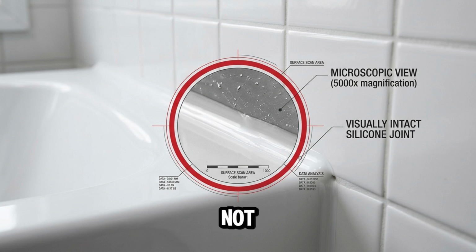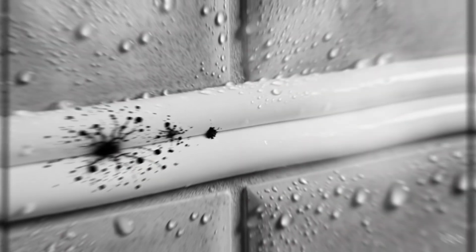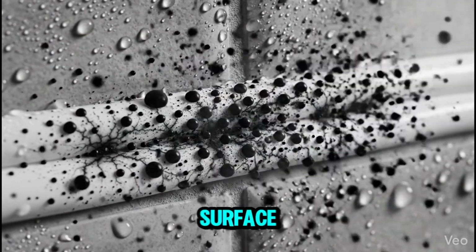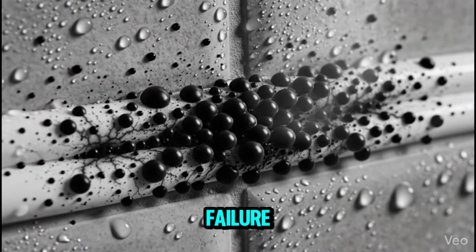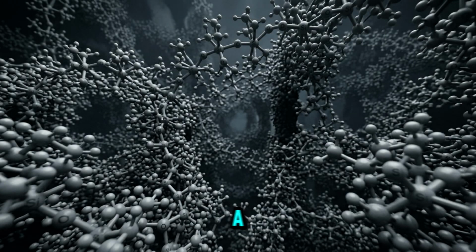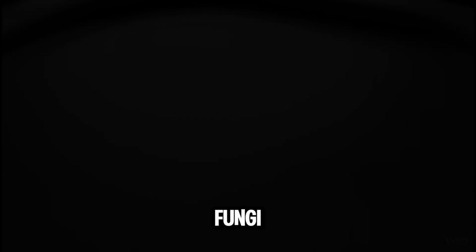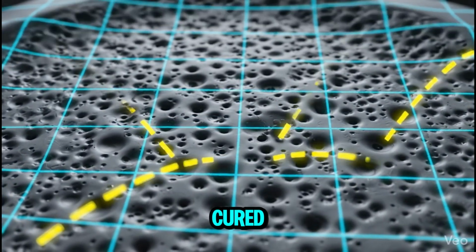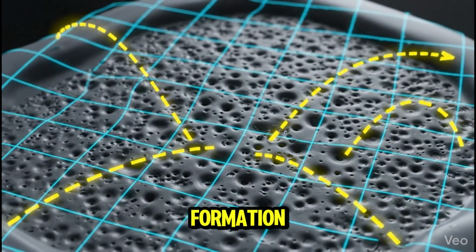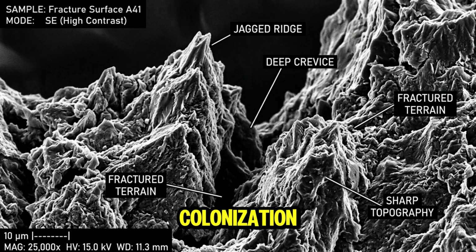The failure mode is not a physical one. Silicone does not crack under normal residential conditions. It does not peel away from a properly prepared surface in the short term. The failure mode is biological, and it is built into the material's chemistry in a way that manufacturers have understood for decades. Silicone polymer chains contain no nutrients for fungi or bacteria. The material itself is inert, but cured silicone has a surface microstructure that is highly favorable to biofilm formation, the first stage of mold colonization.